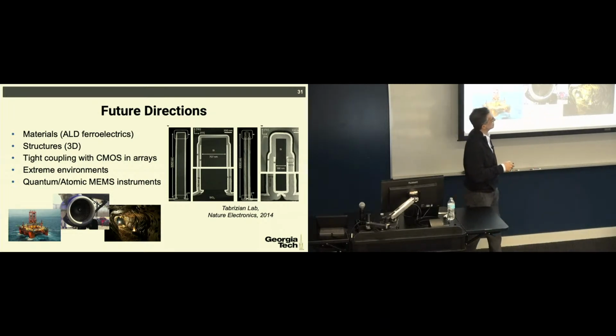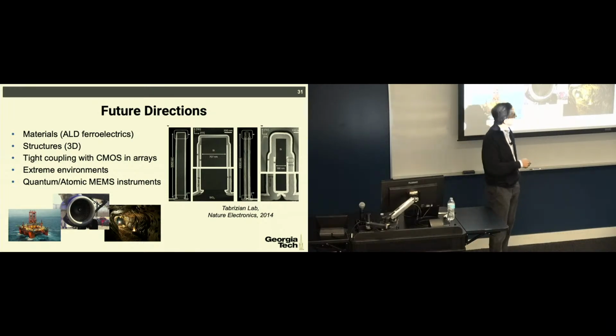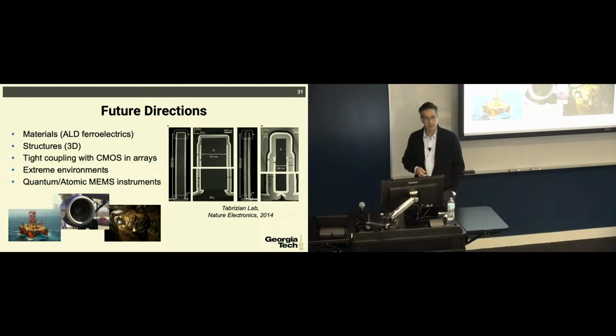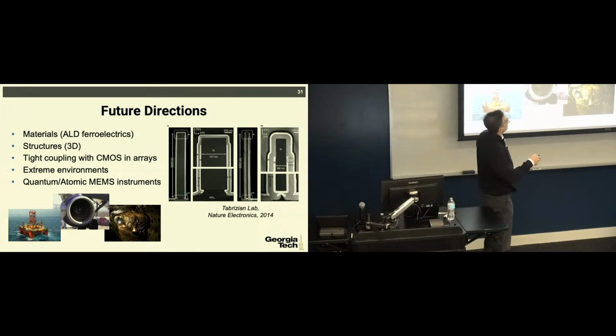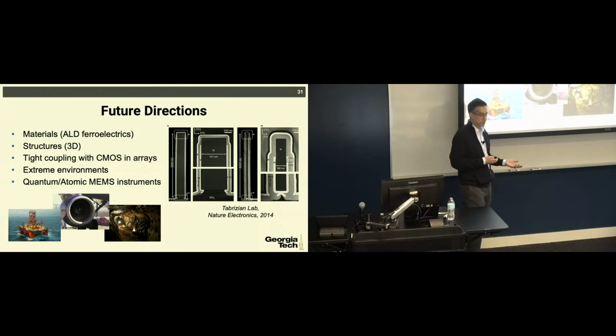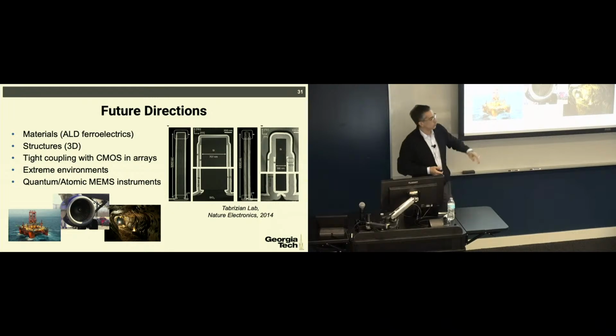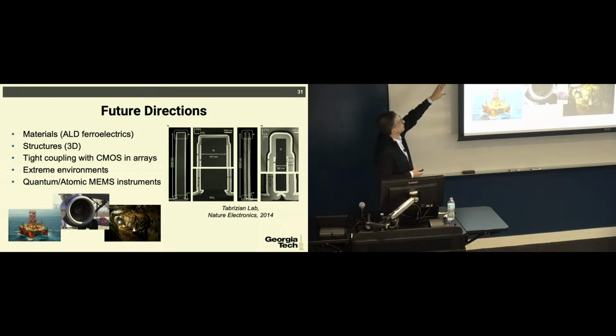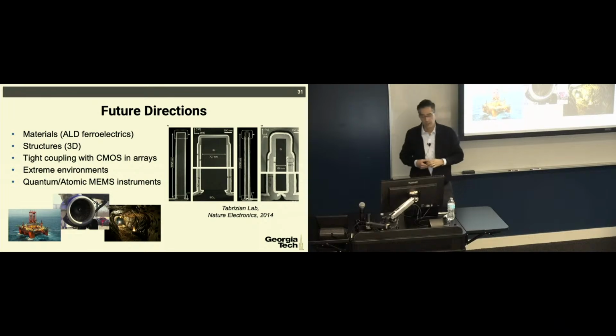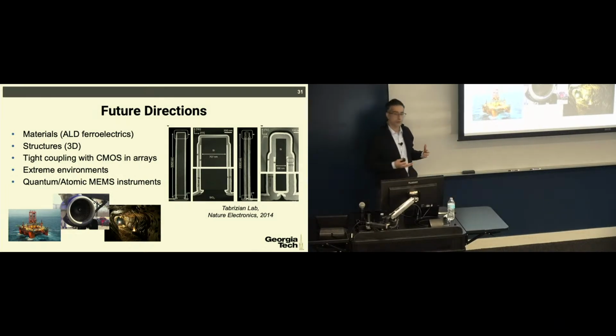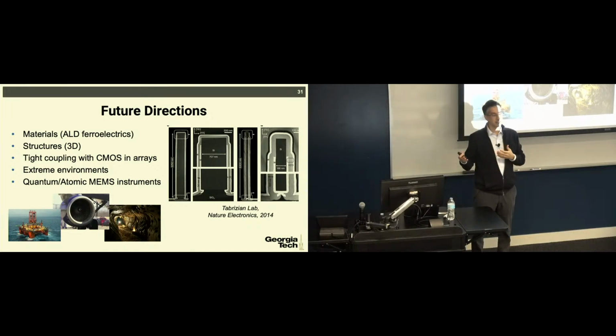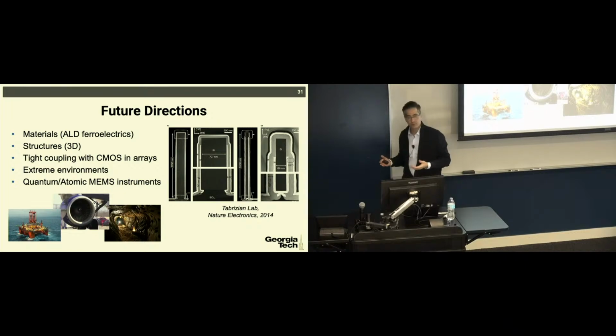And what you see here is a silicon fin, very much like a FinFET, that is coated by piezoelectric layers deposited through an ALD process. So this is a hafnia zirconia layer of piezoelectric material. It's a ferroelectric, but you can use it as a piezoelectric as well. And you can actually now use this fin, the three-dimensional fin devices, as resonators for frequency filtering applications. So there will be a lot of space for material exploration, for structures, 2D versus 3D, tight coupling with CMOS in arrays. Arrays of resonators can be used for enabling still holy grail type of problems like e-nose, electronic nose. We've been working at it for a long time.